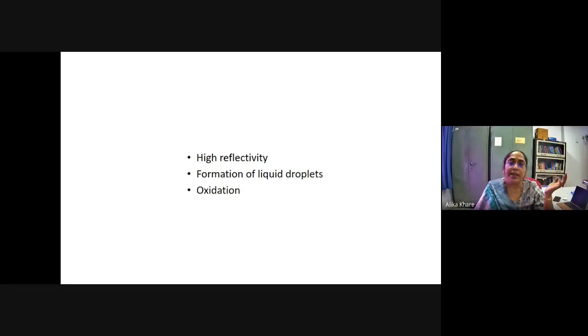Another problem is, since the melting point is not very high, and since they are good conductors, the material partially comes out in the form of liquid droplets, which may get deposited onto the substrate, giving a very poor quality film. Then, of course, the oxidation - particularly once dealing with copper and molybdenum, etc., they are prone to oxidation, so the vacuum quality has to be extremely good. These are the three challenges we face, but with proper optimization and carefulness, one can overcome all of them.